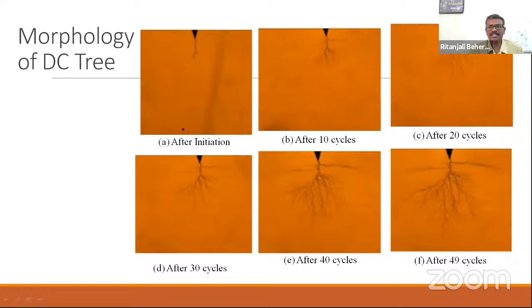This is the result of the DC tree. This is the morphology immediately after initiation, that is, after application of the impulse voltage. After 10 cycles, this is the tree branching. After 20 cycles, we are able to see it has grown a bit more. After 30 cycles, yes, it has grown a little. After 40 cycles, it has grown even bigger and longer. And after 49 cycles, it has almost reached the ground electrode. At the same time, it was also radially spreading.